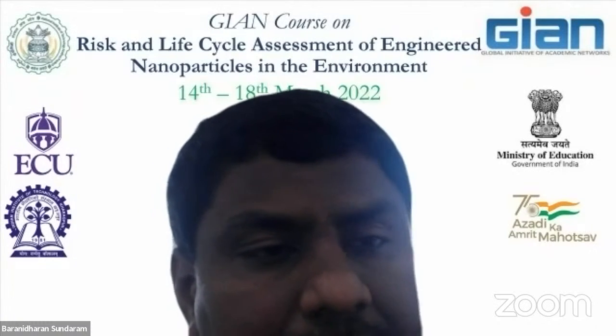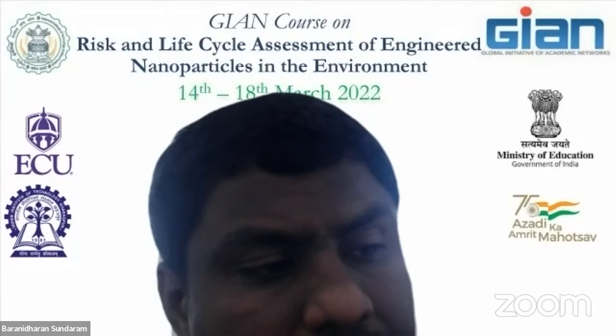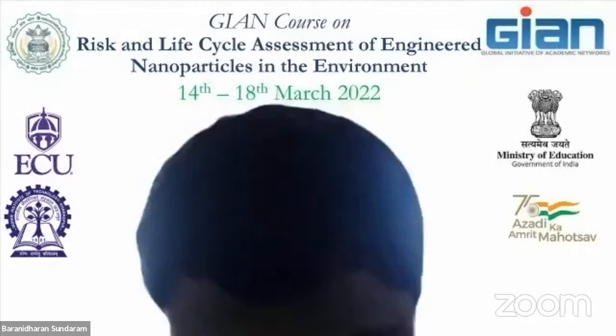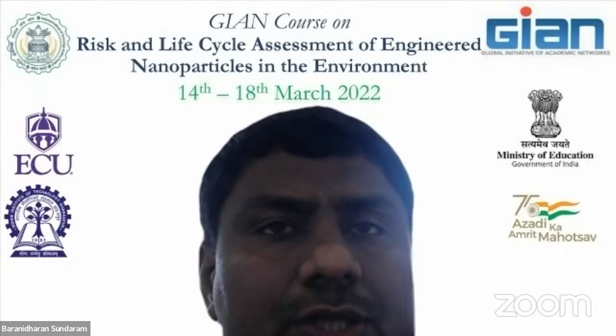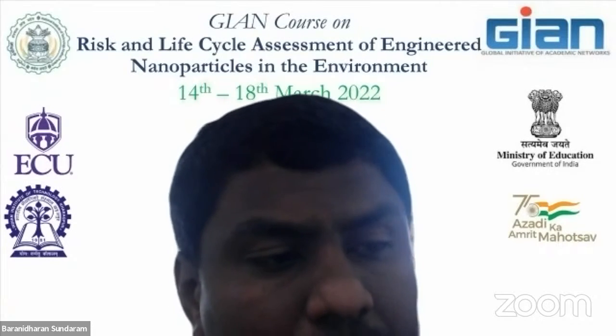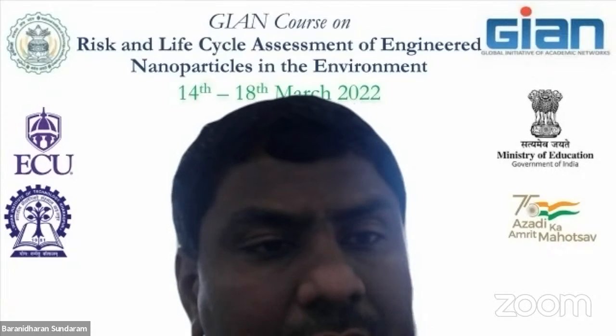See, the filtered sample without digestion was taken for DLS, and the hydrodynamic diameter was determined, and the sample that was collected after filtration was taken to digestion, and through ICP we could get the metal ion concentration. Nanoparticle concentration, how can we arrive at it? That's what we could not see. We are not directly in a position to arrive at the nanoparticle concentration, but with respect to the elemental concentration, we could correlate the presence with respect to the DLS as well as TEM. We could say that this can be there from the nanoparticle source.